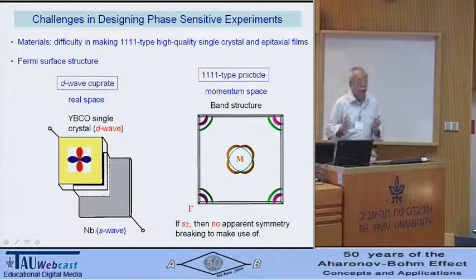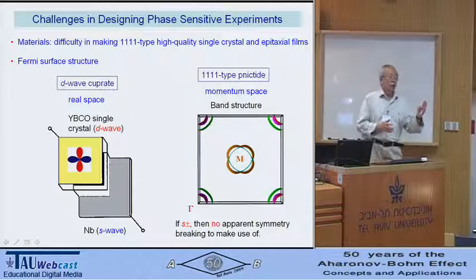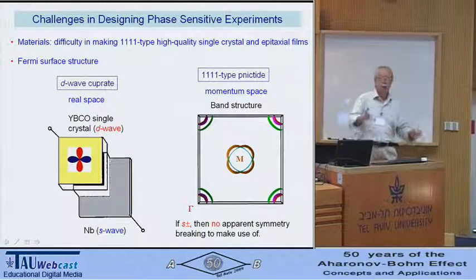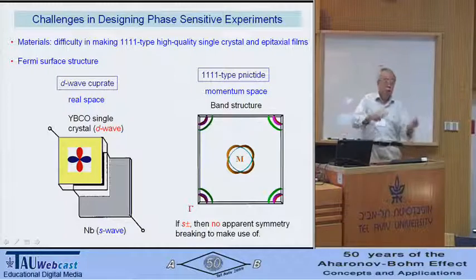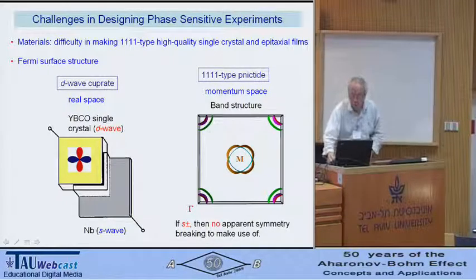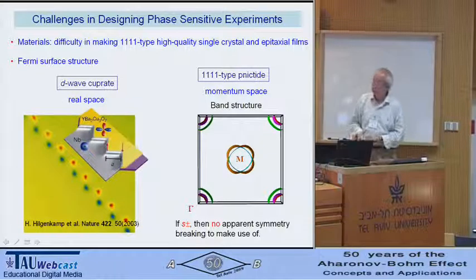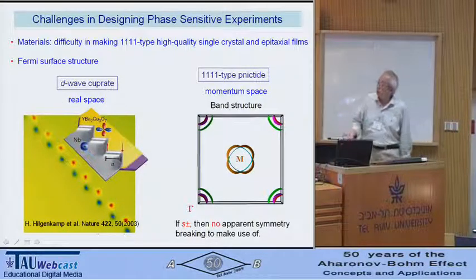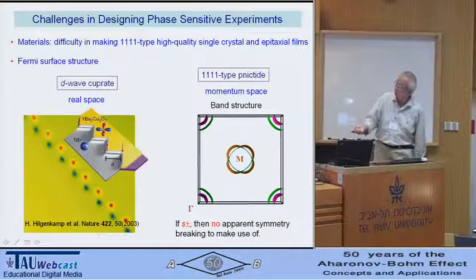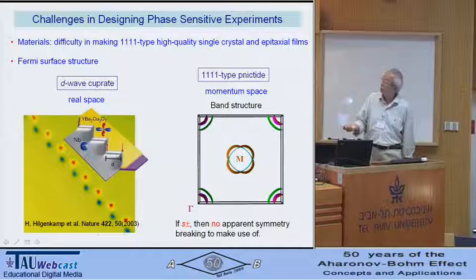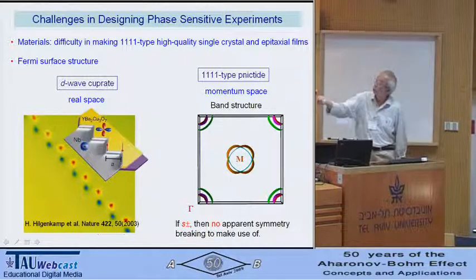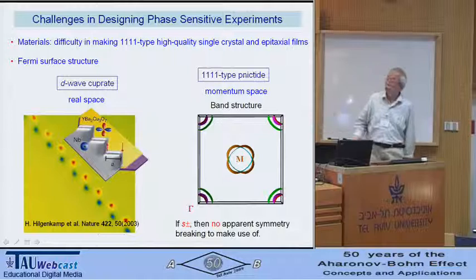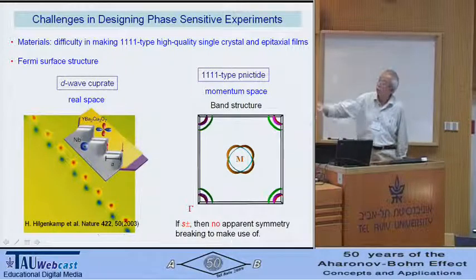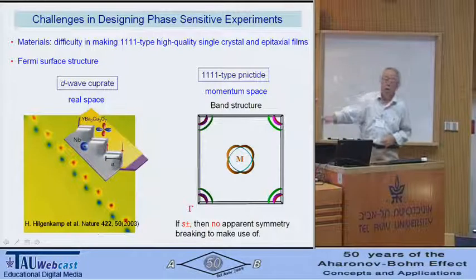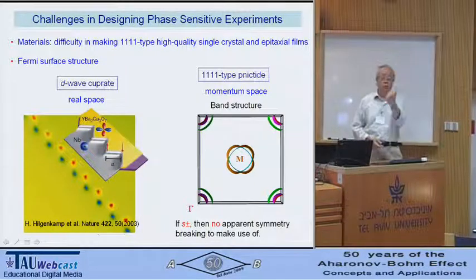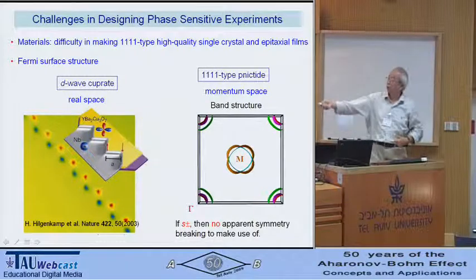So it's relatively easy because there is a one-to-one correspondence from the K representation to the R representation. So you can design an experiment like this with relative ease. Here it just shows one example, which we published in a paper in Nature in 2003. Again, there are the corner junctions. The corner junction will give you the half flux quantum effect, which shows as the zigzag pattern of a half flux quantum. One is up, one is down, because they are antiferromagnetically coupled. So that's what you get.